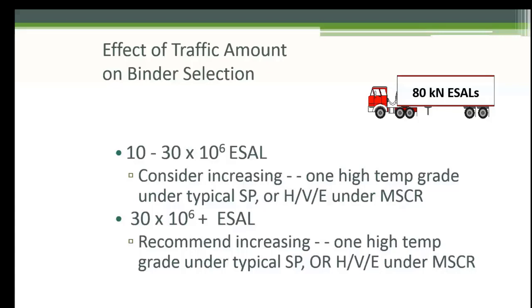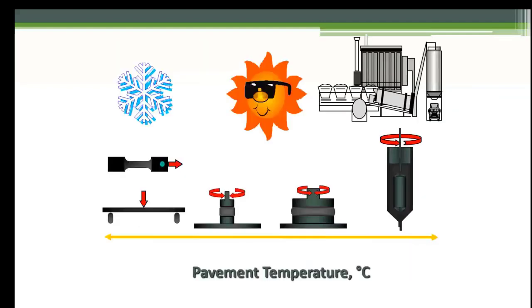And so essentially we're trying to fool the system. And so what came out of that was kind of this MSCR method, multiple stress creep recovery. But I'll get into that here in a second. But basically what PG binder did as a specification, as a testing method, is try to accommodate the asphalt liquid under all conditions. Far left there is the extremely cold pavement temperature, where that pavement's trying to contract, maximizing those stresses in that pavement, which at some point doesn't take traffic, pavement will snap.